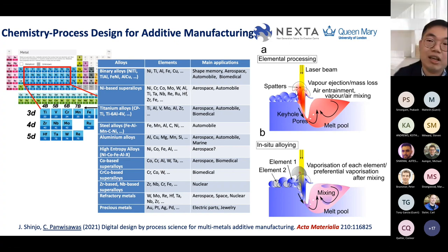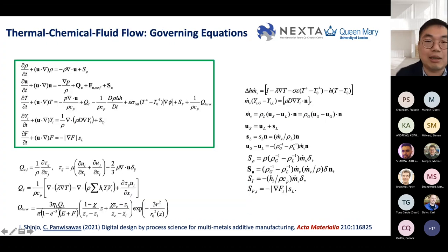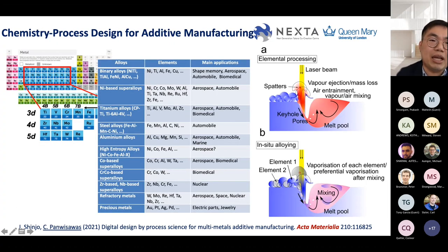application. For example, in the biomedical application, when you have a binary system, nickel-titanium system, where the nickel actually lost a lot compared with titanium, and then you have to understand how this happened and how can we compensate the percentage that lost by the process condition. So this is the ultimate goal of working on this, but we want to generalize this into the whole 3D, 4D, 5D transition metal, and then select some material which is available in the aerospace, automotive, and biomedical area.